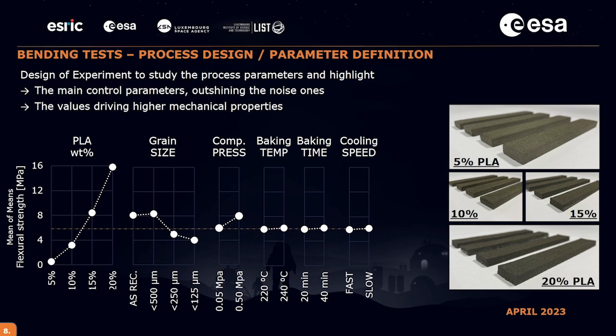We had different numbers of levels, so you have 4 levels for the PLA weight percentage, 4 levels for the grain size, and two levels for the other parameters. And you can see that this investigation told us that baking temperature, baking time, and cooling speed do not play a significant role, which means that we can have the bricks really fast because we can cool them faster. We do not need long baking times. See that we are talking about 20, 40 minutes, and we do not need high temperature. We only need to melt the polymer.